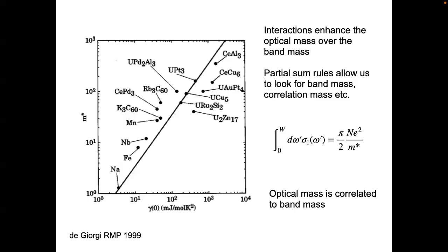It's something that we're interested in, and I have some hopes that we can either look for it or at least probe for this kind of thing in some of these cyclotron resonance experiments we do at high magnetic fields. Cyclotron resonance is notable in that it picks up contributions to the renormalized mass in a very different way than other quantities. However, there's an idea about Galilean invariance and Kohn's theorem. Materials like heavy fermions or cuprate superconductors are certainly far from being Galilean invariant. But these are important considerations that come in, and in principle can be looked for. Nobody has ever seen that as far as I know.